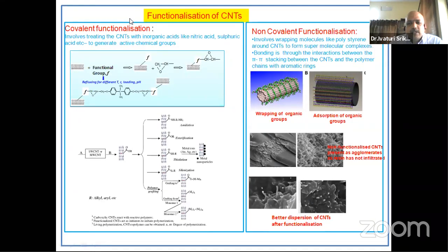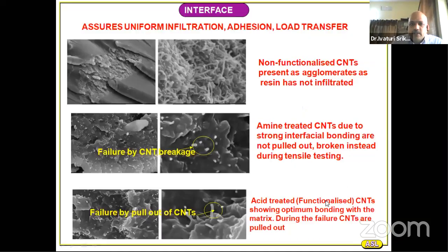So to overcome that, people have also come up with non-covalent functionalization, where long chain organic molecules with certain polar groups will be wrapped around the nanotube. This in turn will bond with the binder. So these are some of the types of functionalizations. You can see here a non-functionalized CNT, as received CNT, if you add it, it will agglomerate without any dispersion. When you disperse functionalized nanotubes and add them into composites, you can see how the individual CNTs are well dispersed. These black color thread-like structures that you are seeing are functionalized CNTs dispersed in the matrix. So that is the effect of functionalization.